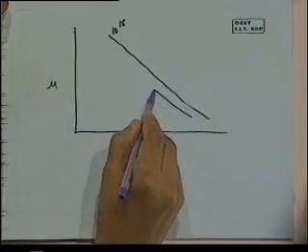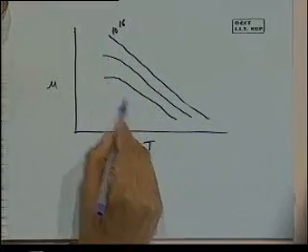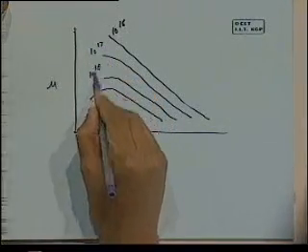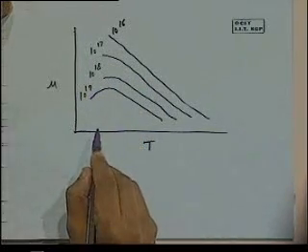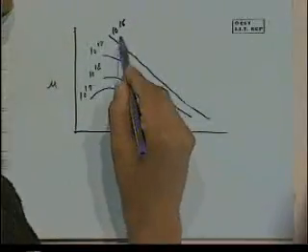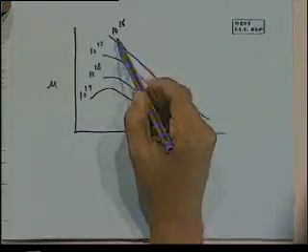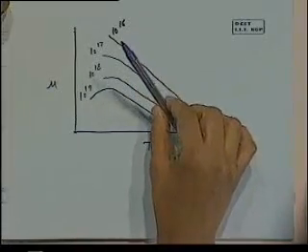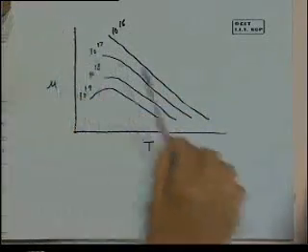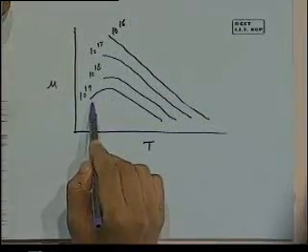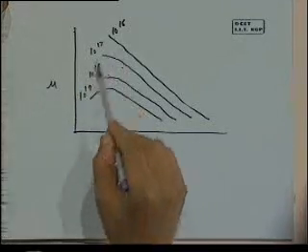As we increase the concentration, the effect of ionized impurity scattering becomes more and more predominant, so the curve begins to shape downwards. At very low doping densities, ionized impurity scattering is not very important unless you go to very low temperatures. But as we increase the doping concentration, ionized impurity scattering kicks in more and more. This is how we look at both the temperature effect and the effect of ionized impurities.